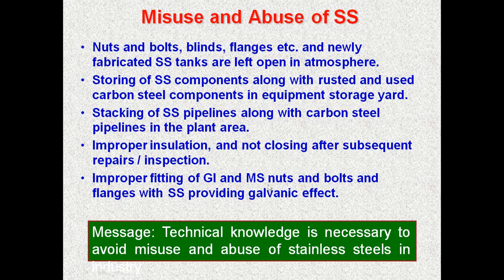Improper fitting of galvanized iron and MS nuts, bolts and flanges with stainless steel provides a galvanic effect. People think that from a strength point of view or economic point of view, they can use galvanized iron or mild steel nuts and bolts for a stainless steel pipeline. That's very, very dangerous. This is mainly because technical knowledge is not there, and it is necessary to avoid such kinds of misuse and abuse of stainless steel in industry.